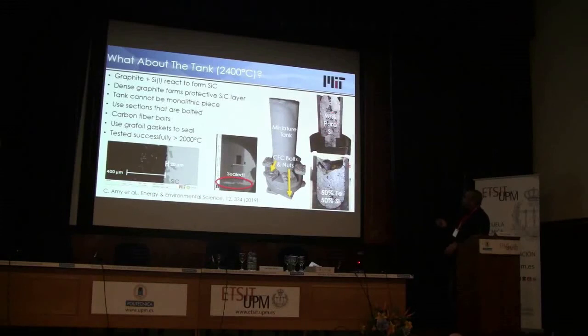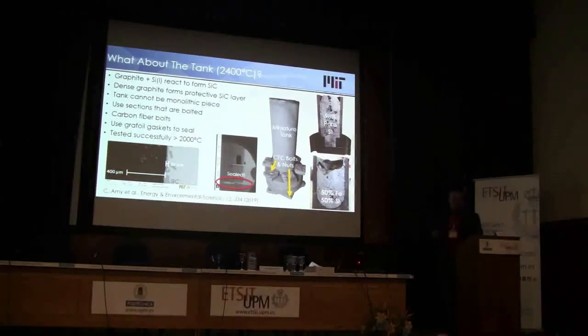The silicon carbide is what essentially helps us as a seal. So we've done that with metallurgical grade silicon. We've also done it adding 50% iron. So if you start with silicon first, get silicon carbide on all the walls, then you can add 50% iron, and then these two can sit in contact with each other, thermodynamically stable. So you do not eat into the wall. If we increase the iron content, let's say you go to 100% iron, what you'll find is the wall will be recessed. It's actually dissolving the carbon. It gets through and starts to dissolve the carbon. And so one of the cool things about operating this hot is everything happens really fast. So you don't have to sit and wait for 100 hours to see if something's going to happen. If it's going to happen, it'll happen in a few minutes, and you'll see it. So all of these results are discussed in a paper we have in EES.